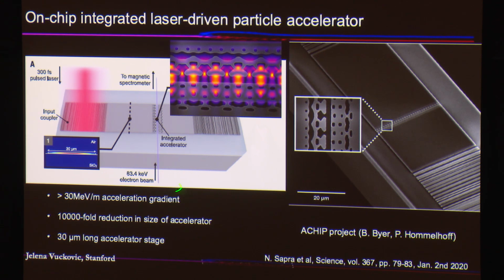They have an energy of around 80 kiloelectron volts. So in a single stage, we can accelerate them with this gradient, 30 mega electron volts per meter. And we can, in principle, miniaturize the accelerator by about 10,000 times. So as you see from the results that I'll show you in a moment, if we cascade about 1,000 of these elements, we should be able to go from 80 kiloelectron volts to about a mega electron volt. And mega electron volt is already very interesting because we can think about some medical applications or imaging applications. It's not state-of-the-art high energy physics, but it's already interesting for a variety of applications where accelerators are used. And it would be only 1 inch of silicon.